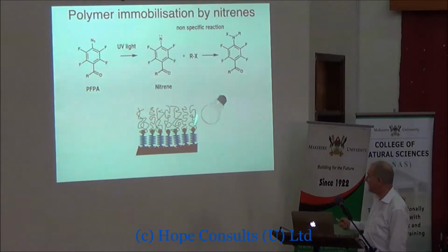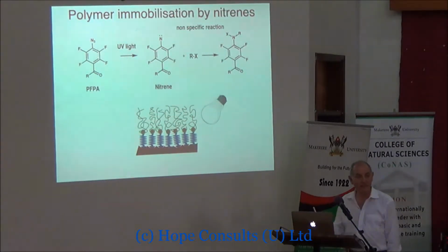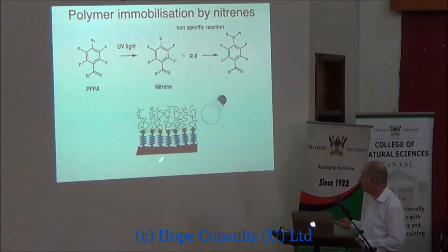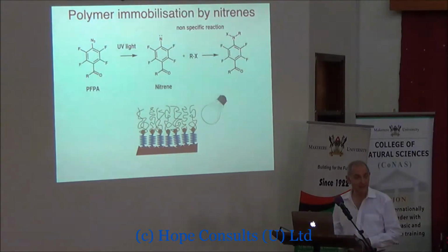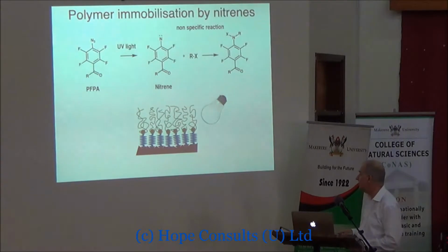What we've made here is something like a polymer brush. It's not quite as tidy as the polymer brushes I showed you before, because these chains can attach anywhere along their length, not necessarily at their ends. But it's a way of fixing a polymer onto a surface, and if we choose this anchoring group correctly, we can attach a polymer onto almost any surface. It can be another polymer, for example, or a metal, or a ceramic, or anything. And this just shows, for the chemists, the one reaction that's important here. We have this R group that attaches it to the surface, and we have this nitrene generator, which is N3 at the end.